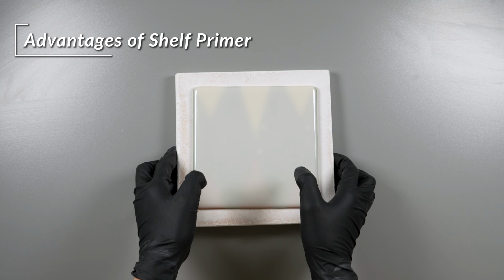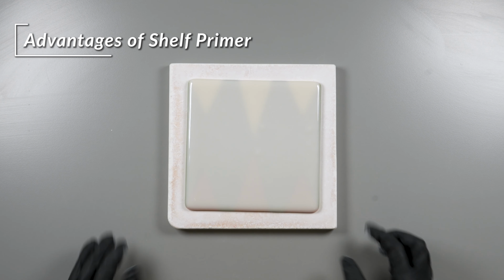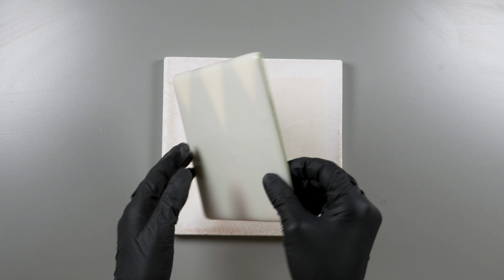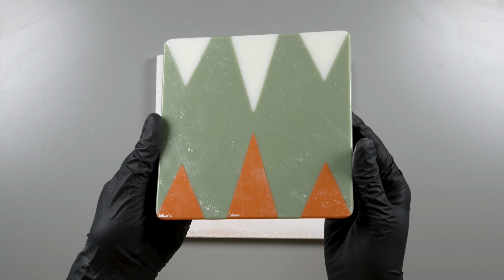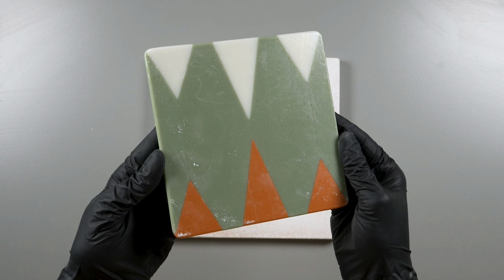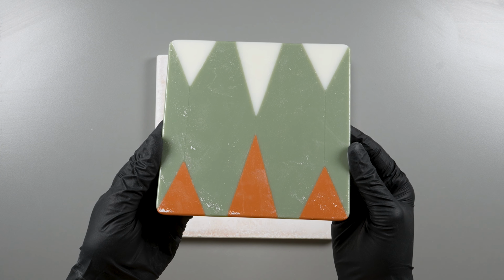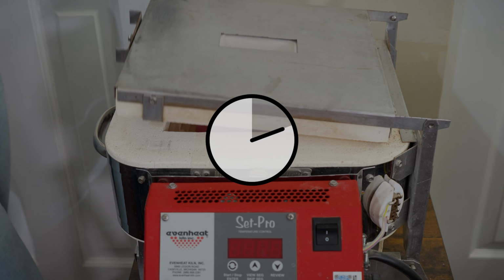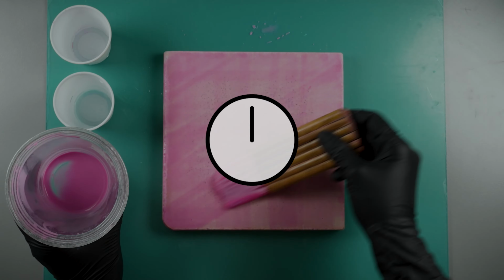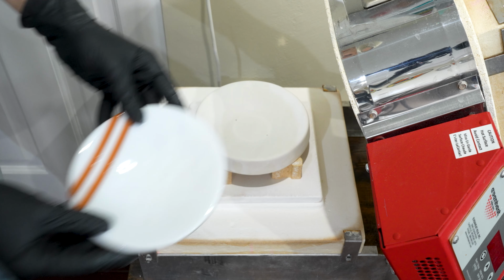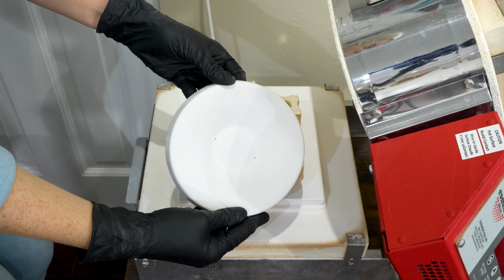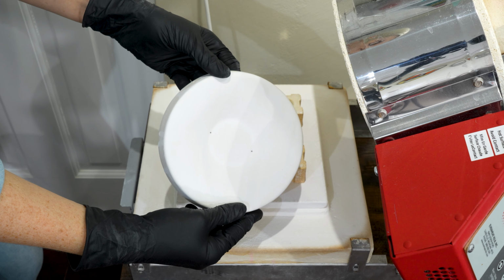An advantage to using shelf primer is that it's much cheaper than shelf paper. With proper application, it also leaves glass with a very smooth finish, imparting little texture, and it poses no risk of triggering devit. Primer's biggest disadvantage is the time it takes to apply and clean up. Depending on the brand, it has to be removed, reapplied, and dried between every firing, which can really add up for frequent fusers. The exception to this is when it's heated to slumping and draping temperatures below 1300 degrees Fahrenheit, in which range it can be reused multiple times.